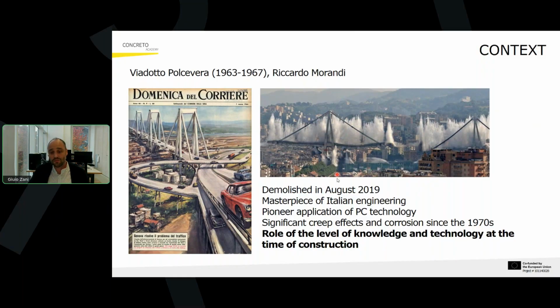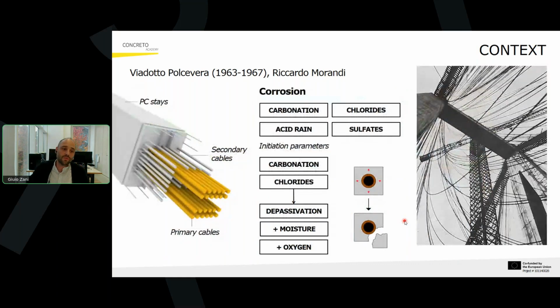This was a pioneer application, but since the 1970s, significant creep effects and also corrosion at some points of the structures were observed. And we always need to keep in mind the level of knowledge and the technology at the time of construction, because this was, as I mentioned, a very brave application, one of the first of its kind, due to the presence of these pre-stressed concrete stays, which consisted of a set of different cables. So we had primary cables and secondary cables made of high-strength steels.